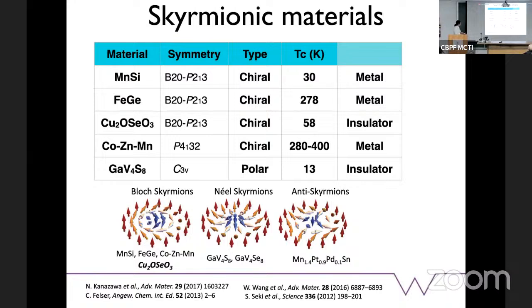Of course, the cobalt, zinc, manganese, again, is a chiral space group, and this is a polar space group. So the skyrmions that I told you about can stabilize in several different forms of spin arrangement. The spin textures, the way they are arranged, can be different, and they are classified as Bloch skyrmions, Néel skyrmions, and also anti-skyrmions. And if you see the pictorial depiction of how they are organized, in the Néel skyrmions the spins are coming out from the center, and for the Bloch skyrmions they are going into the center. And then for the anti-skyrmions, you have half of each of these.